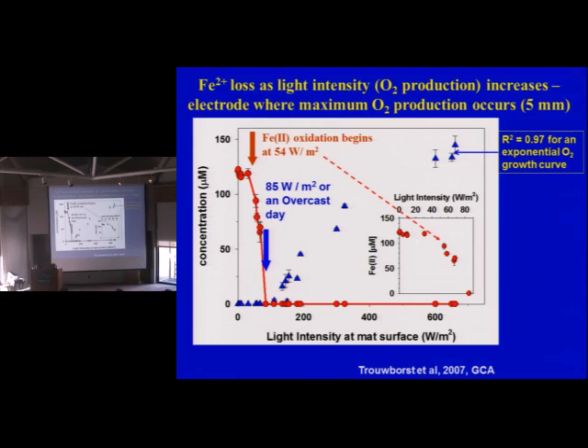Now what happens is you increase the light intensity upwards to what we would now have today. You'll notice you get this kind of curve. And it's a typical exponential growth curve that you would see for something that's light dependent. And it's a pretty good fit. And so this tells us that this is a light dependent reaction and everything's going well. At some point you're going to shut down photosynthesis because they're going to be inhibited. Now remember, this is the light that's actually right at the surface of the mat. It's not 0.5 millimeters below. It's right at the surface. But this gives you an idea of what's going on.